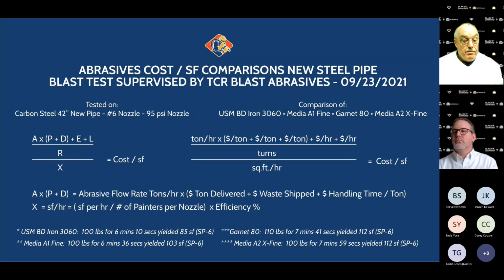So the media A1 fine, which was actually the first video, those were 100-pound bags, and that lasted 6 minutes, 36 seconds, and actually had 103 square feet. The garnet was 110 pounds, 7 minutes, 41 seconds, 112 feet. And the extra fine was 100 pounds, 7 minutes, 59 seconds.